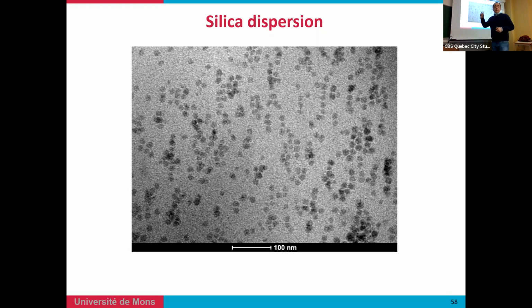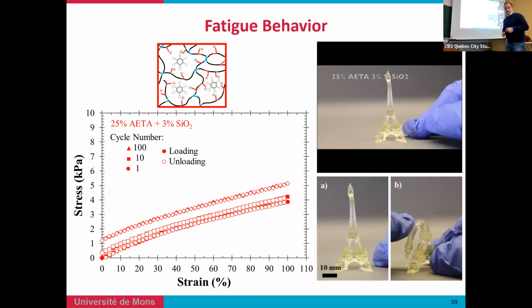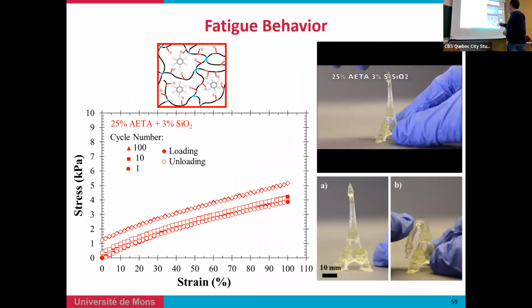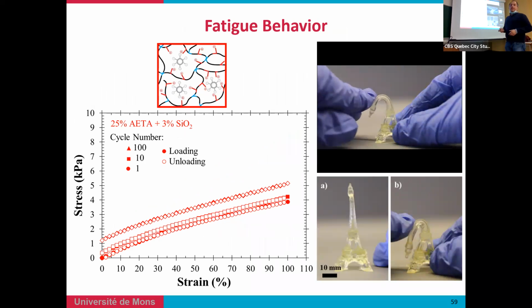Of course, what is very important is also to maintain a very nice dispersion. In fact, through this type of interaction, you can see by TEM images that we have individual dispersion of the nanoparticles at the end. The most interesting feature is the deformability.